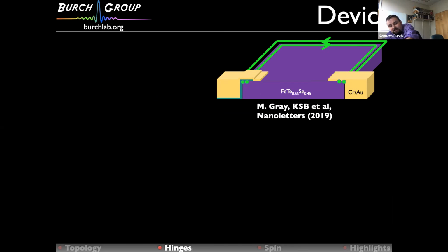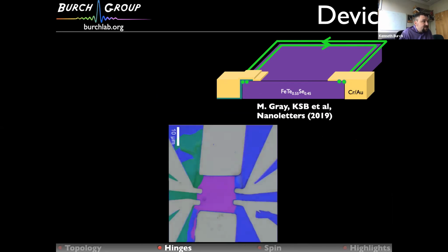So here's the cartoon of what we were going for, and here's the actual device. And I'm going to show you data from one, but we have data from multiple devices. Okay, so we have our iron telluride selenide exfoliated here. We put big current leads on just so we could do 4-point measurements and check that it was really superconducting. We put our HBN here such that it covers one of the hinges on one side. And then we have these voltage leads, which we split so we could use them like point contact leads.